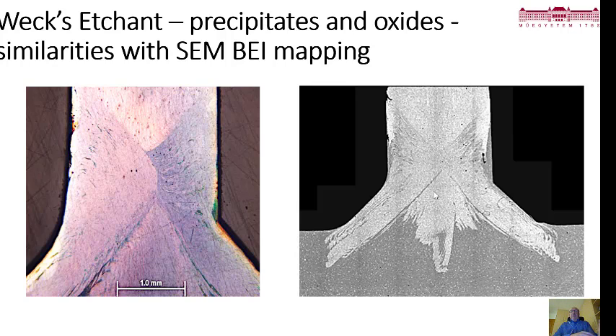So now we looked at Weck's etchant. It's another electrolytic etchant which reveals precipitates and oxides. Notice that the grains are not revealed here, or flow lines, like in the Barker's etching, but it just incredibly resembles the EDS mapping. So you can see that Weck's is almost identical.